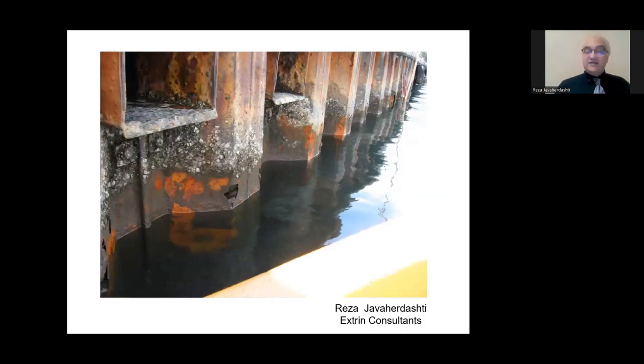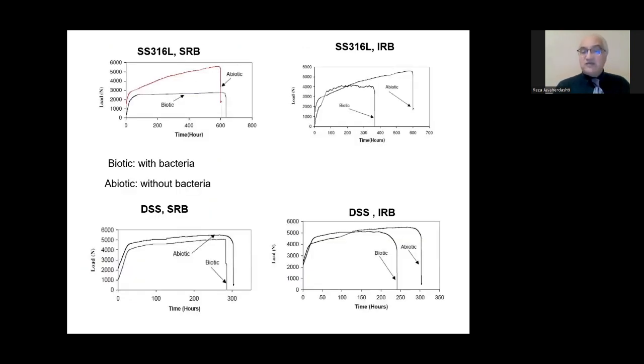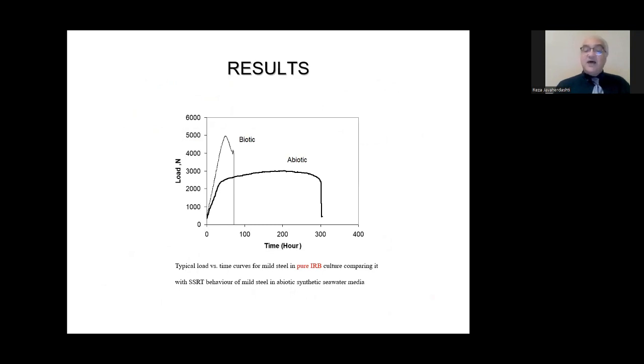This is an example that we had in Papua New Guinea, where due to impact of SRB and iron-reducing bacteria, we got very severe pitting and corrosion in such structures exposed to low water corrosion. Stress corrosion cracking can also be enhanced by the impact of bacteria. To the best of my knowledge, I was the first who proved that stress corrosion cracking could be also affected by bacteria. Like here, you have carbon steel affected by pure iron-reducing bacteria, shown as biotic. You see that the time to failure when you have bacteria is shortened, meaning that carbon steel can fail in much shorter time than when you don't have the bacteria.